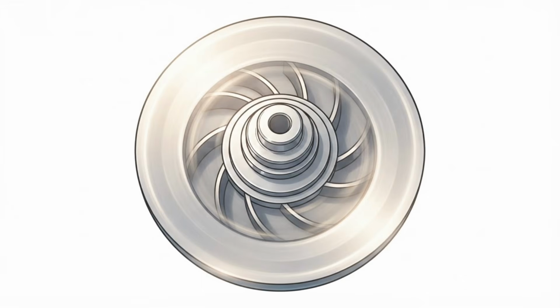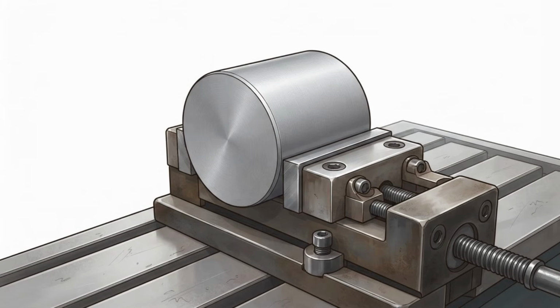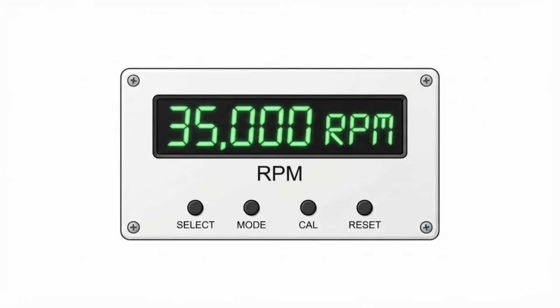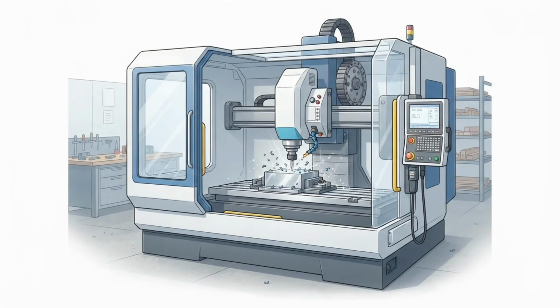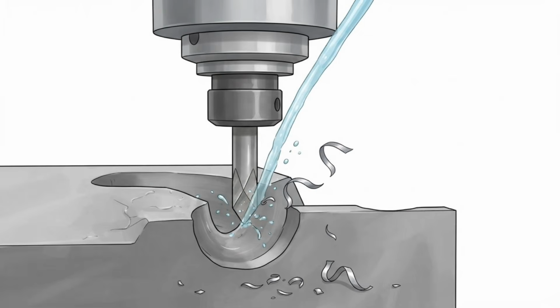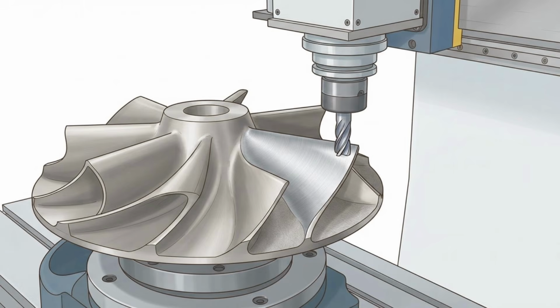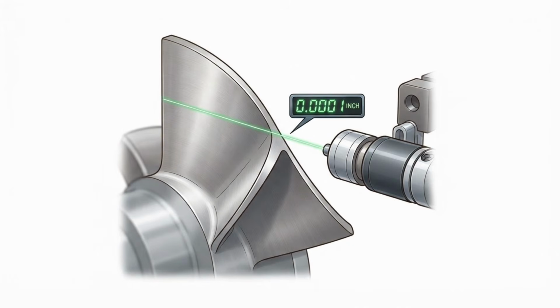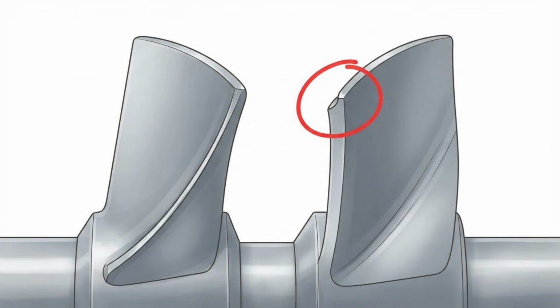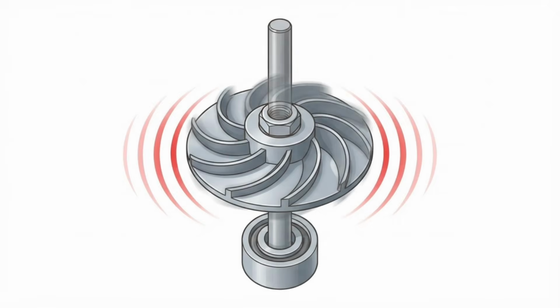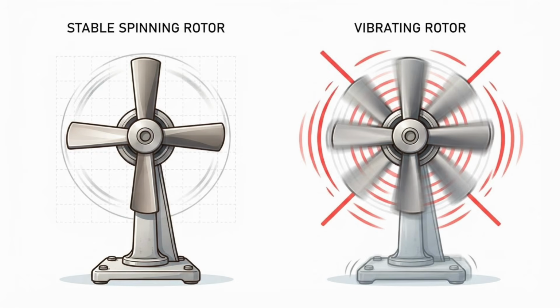These impellers are machined from solid blocks of titanium or advanced superalloys using 5-axis CNC milling machines that carve out the complex, sweeping curves of the blades with tolerances measured in 10,000ths of an inch. If the blades are uneven by even the weight of a paperclip, the imbalance at high rotational speeds will cause catastrophic vibration, tearing the pump apart in milliseconds.